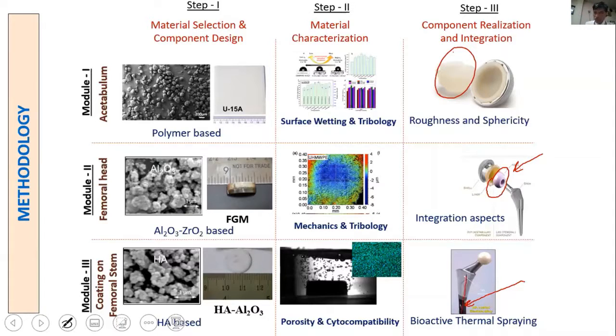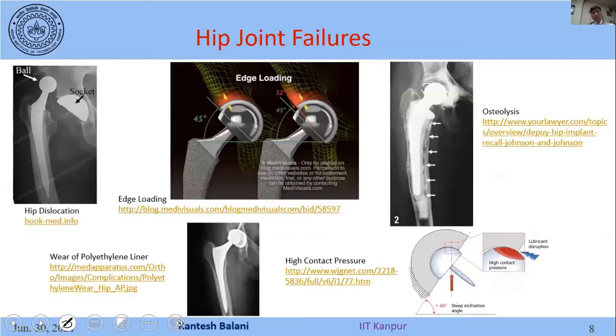Again, you require some coatings and a metallic stem. The metallic stem is to take that impact, and coatings again provide bioactivity. So we have a collage of all these materials, and that's why all these materials are very important. But typically in a joint, mechanics is very important, because if you have a ball and a socket, your liner is very weak. By any movement there can be a hip dislocation because it's a snug fit. You can have an edge loading. Typically at the edges, there'll be a very thin layer of polymer which now comes in contact with the femoral head, and that may lead to damage as an edge loading.